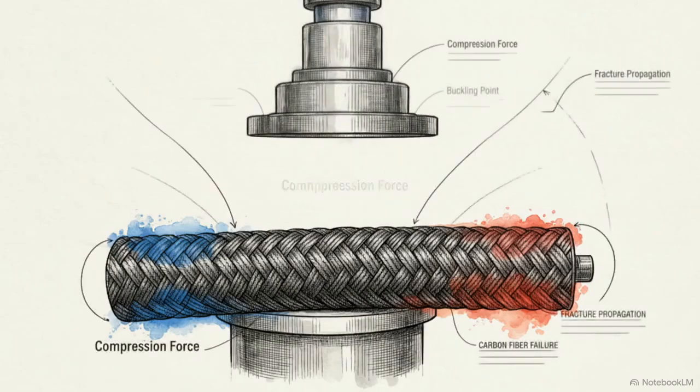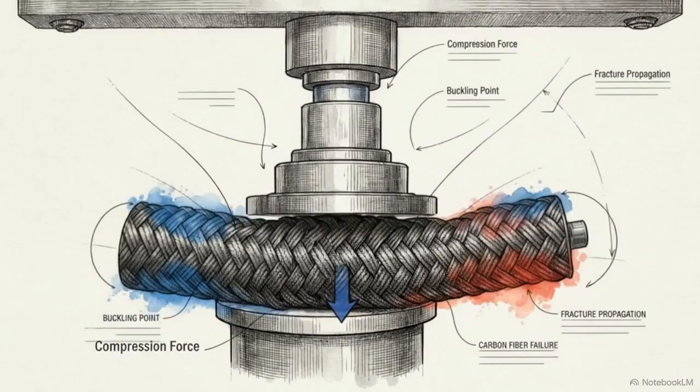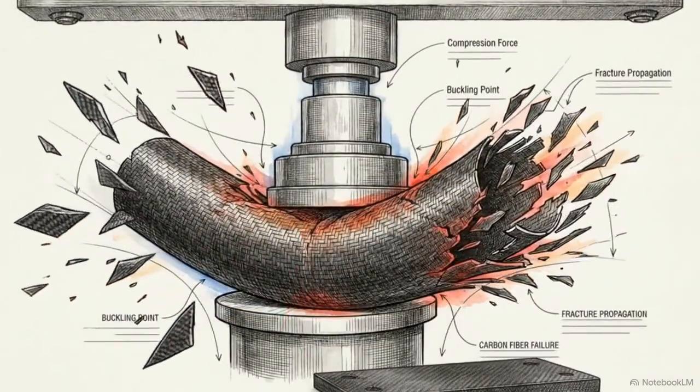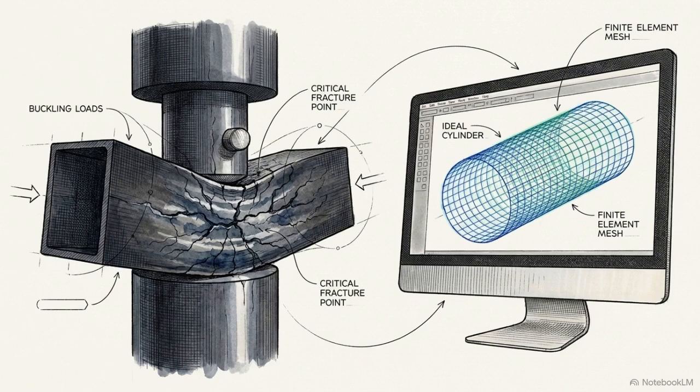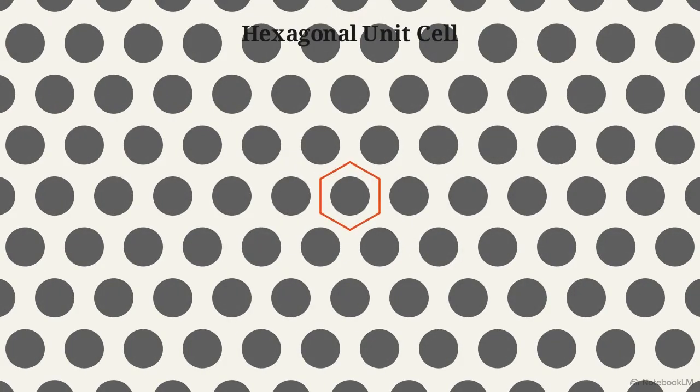When an engineered carbon fiber strut is subjected to immense longitudinal compression, failure is sudden, violent, and complete. To understand why a material with such high tensile strength fails this way under compression, solid mechanics traditionally relies on idealized models. Engineers map the internal composite fibers as perfect periodic arrays, usually arranged in flawless hexagonal or square grids.